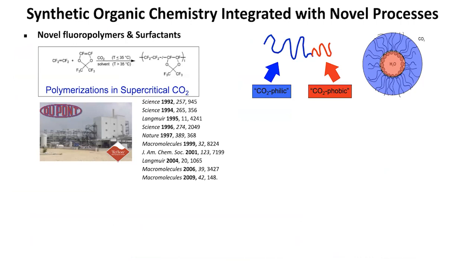polymerizations, where we show that you can do free radical chemistry in CO2. And it was not only chemically inert, but because of low viscosity and high density and diffusion control reactions, you could do some amazing things and make high quality products. We could design surfactants that can self-assemble in CO2. And as you change the density, you can change the degree of self-assembly.